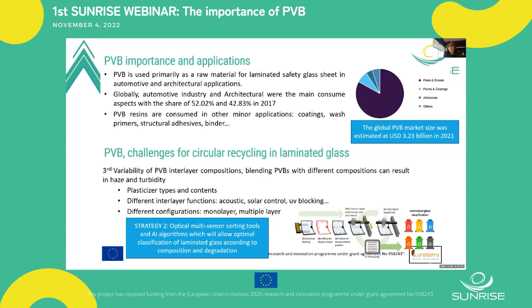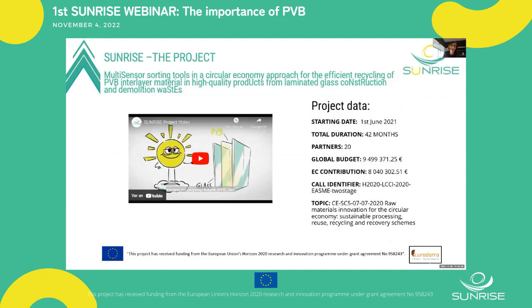And for the third challenge, the variability of PVB interlayer compositions, we have another strategy in the project. This strategy is related to identifying not all aspects of composition, because this is difficult or impossible, but we would like to detect some aspects of composition or degradation that could allow us to sort the laminated glass waste at origin and recycle according to the different qualities and degradation. So for this, the strategy in the project is implementing optical multi-sensor sorting tools, and also developing and integrating artificial intelligence algorithms, which will allow the classification of the laminated glass according to the key parameters of composition and degradation.